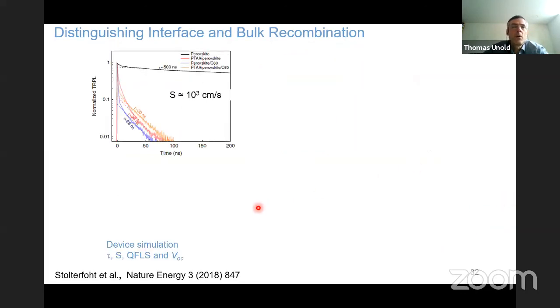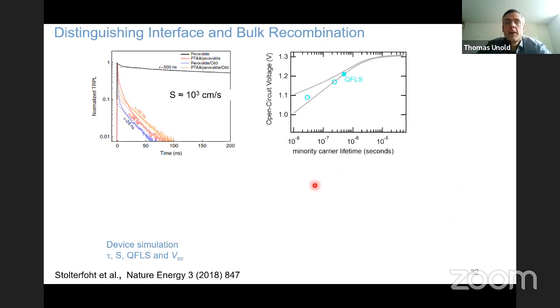We also did some lifetime measurements on this. For the bare film, we found a lifetime of about 500 nanoseconds. And for these contacted layers, this is the charge transfer region and this is the interface recombination region, about 30 nanoseconds. And if you plot this on the plot that I showed in the beginning of this presentation, actually it should be the quasi-Fermi level splitting, not open circuit voltage, versus the measured minority carrier lifetime, you can see that they nicely fall onto this expected theoretical curve. So it's not always easy, but it is possible to really get a consistent data set on this.